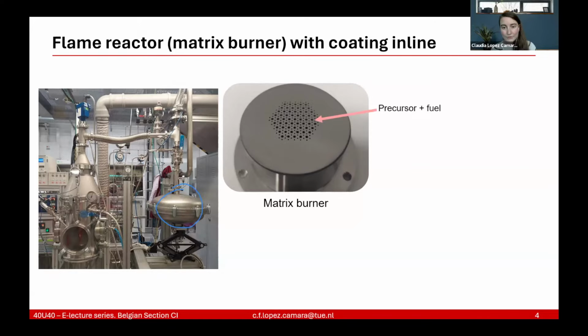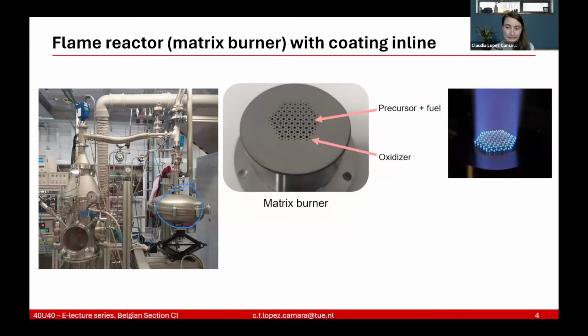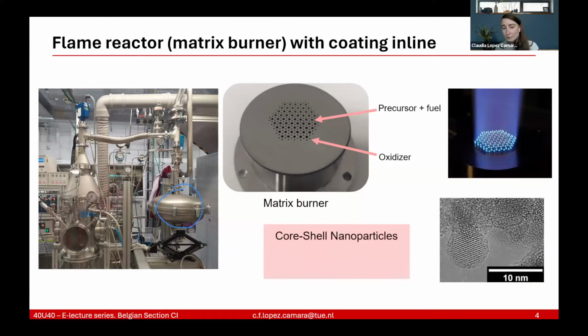So you have the precursor and the fuel coming from the big holes, and the small holes are the oxidizer, oxygen, coming out from it. So when it's lighted up, it looks like this. And this design has been purposefully thought out so that it's easier to also do simulations about it. So that's why it was developed. With this kind of strategy, we can create core shell nanoparticles, for example. And the core shell nanoparticles look like this.